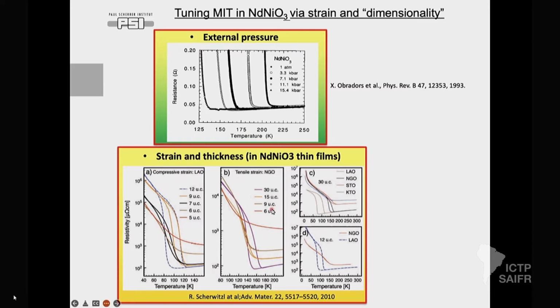But what you could see in these studies is that there is another effect. If you are just looking at one material, so nickelate grown on NGO, and you lower the thickness, there is already a change, because the system goes from something which shows a metal insulator transition to a system which shows to be only insulator for all of the temperatures which were measured. So that tells us that there is something happening in the system with the dimensionality crossover. So not just strain can be used to tune the electronic property, there is also thickness, which you could also see in a similar way with the compressive strain.